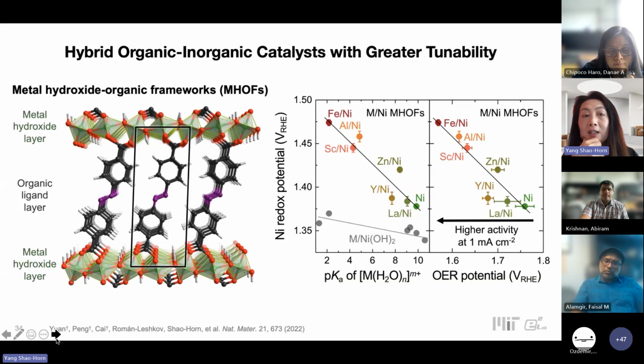To this regard, we have recently developed a hybrid inorganic-organic catalyst. So this is basically the idea. We have a metal hydroxide layer. In this layer, the MO6 units connect with each other by either corners or edges, and these layers are connected by organic linkers. Either through the organic linker or through substitution in the metal layer, we can tune the binding of, let's say, the oxygen site